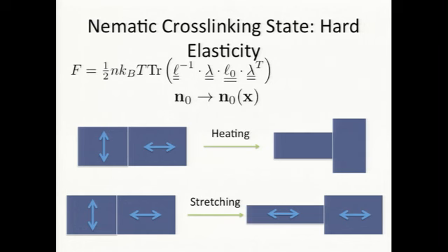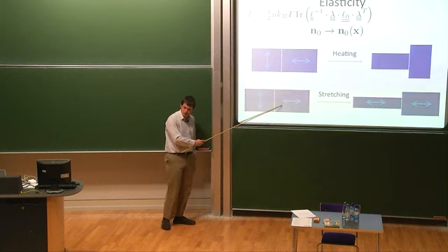Right? Even if we assume these local domains are absolutely perfectly soft, they have no personal domain preference to point this way rather than this way. Okay, they still can't get away from their original state without paying energy penalty because really of geometric frustration, right? They can't do it because this one cannot deform softly without requiring this one to deform as well.